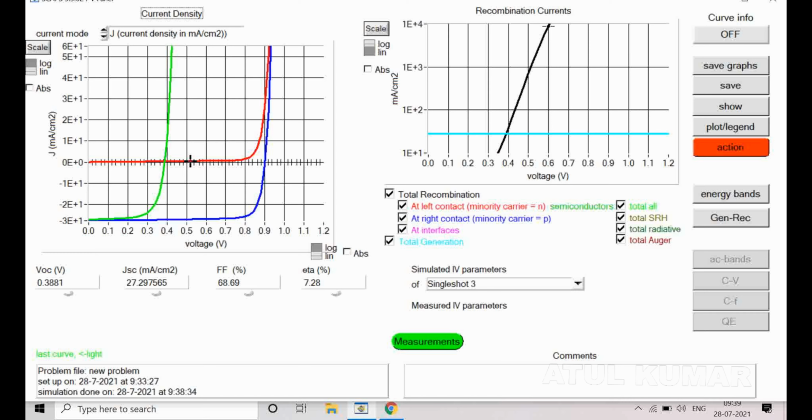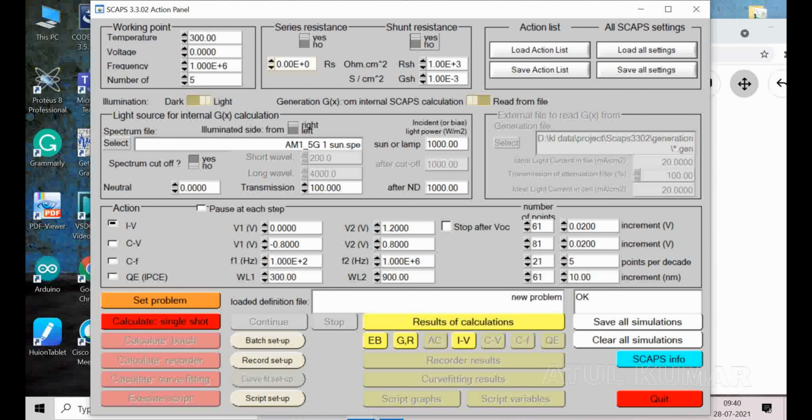So basically this is due to the fact that the Schottky barrier, which is a secondary junction in our device, is aligned opposite to the primary PN junction. So whatever VOC is generated, considerable VOC is being lost at that secondary Schottky junction. So if you do an IV curve, dark and light, and you see crossover behavior, you can directly conclude that you have a metal-semiconductor Schottky barrier somewhere in your device. Okay, so that's the one case.